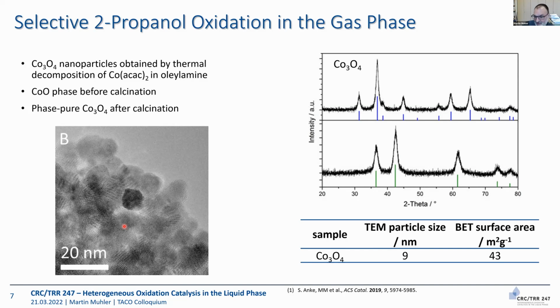We need powder X-ray diffraction to check for phase purity, and TEM tells us that the mean particle size is 9 nanometer. That is rather small for an oxide, and the consequence is that the specific surface area is quite high. 43 square meter per gram, that's quite a lot. So we have many exposed cobalt oxide surfaces. It's a reactive system, and that we can probe nicely using 2-propanol.